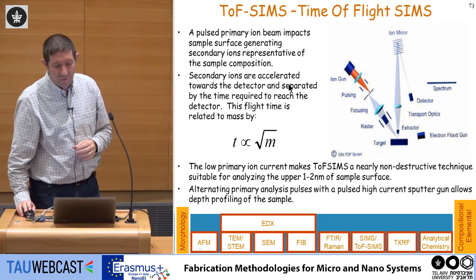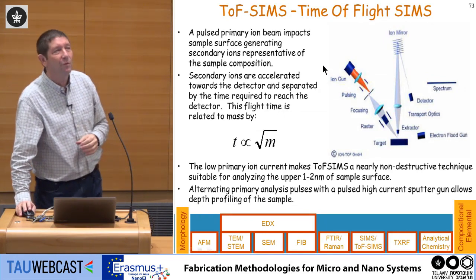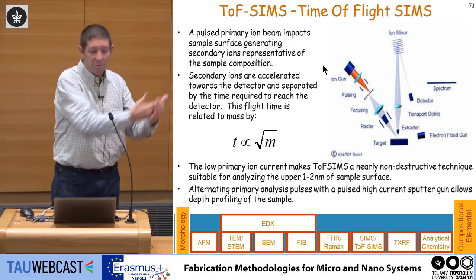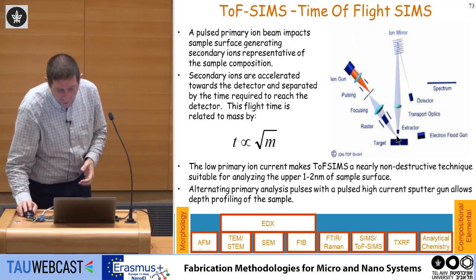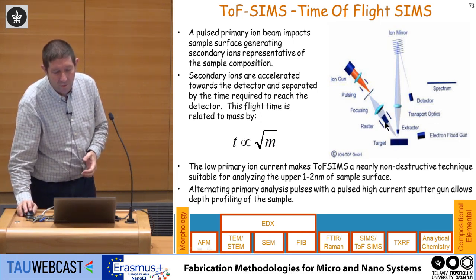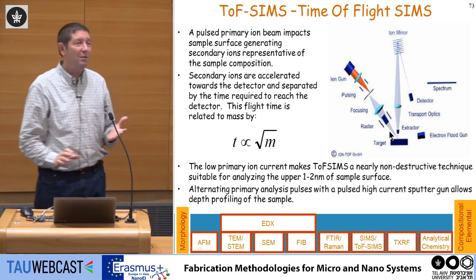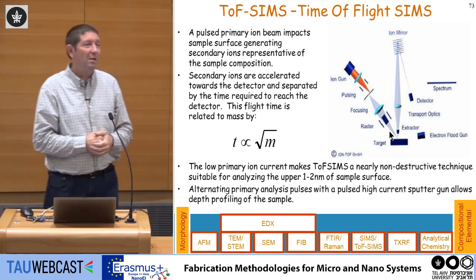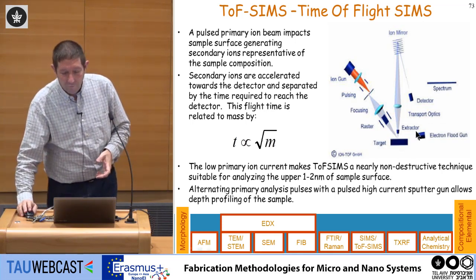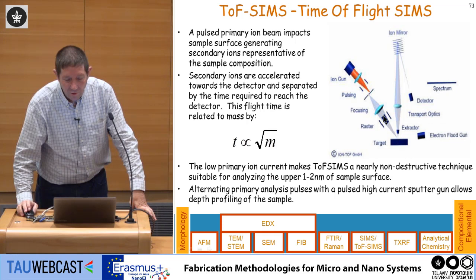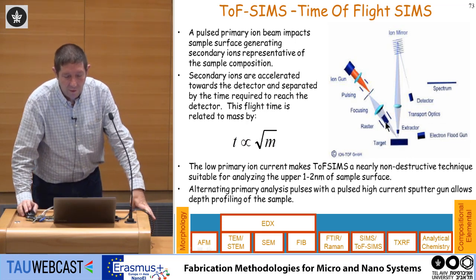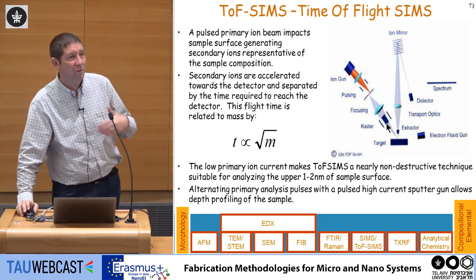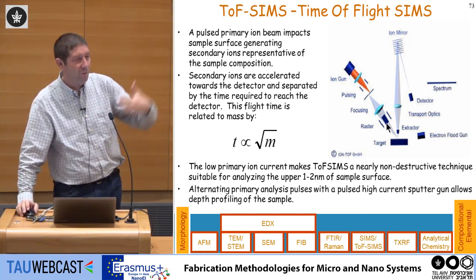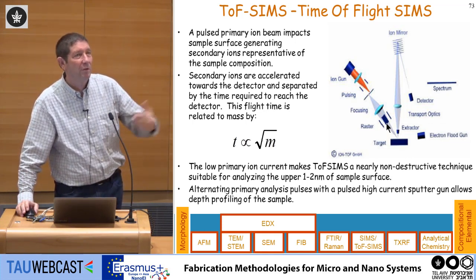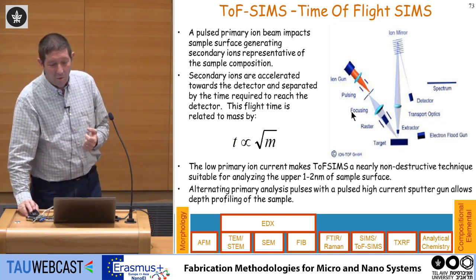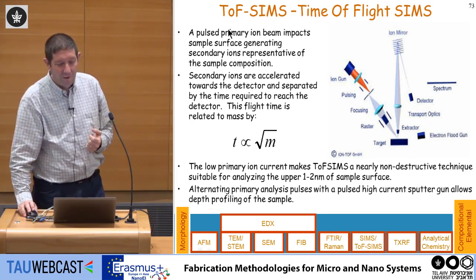Now, a second method, which is also very used, is called time of flight SIMS. Let's say you are sputtering your material. This is the ion gun. It's coming, and atoms and ions are coming out. The best way to measure their mass, or another way to measure the mass, is to measure their time of flight. You give them a certain energy. So if you know the energy that you give to them, you know their velocity. So if you measure their time of flight, how long it takes them to go from point A to point B, you can measure their velocity. So this is called time of flight SIMS.